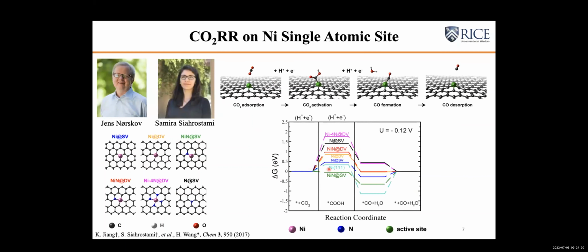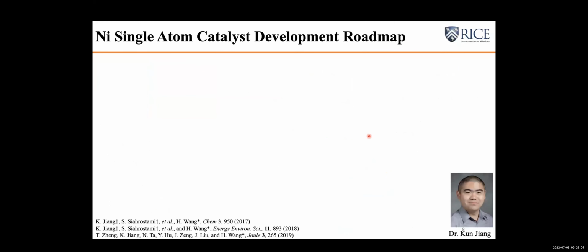If we take a look at the nickel metal first, as we can see, the CO2 activation actually is relatively simple on the nickel metal surface. However, once the CO forms, as you can see, there is a very deep thermodynamic sink that makes the CO desorption very difficult. So it means that the catalyst is not active for CO2 to CO reduction. But if we take a look at this single atomic site, even though the activation process for CO2 reduction is relatively higher than the nickel metal surface, which of course can be offset by applying more negative potentials, the CO desorption becomes much easier. So at that time, it gave us a lot of strong confidence that these types of single atomic sites could be utilized for CO2 reduction.